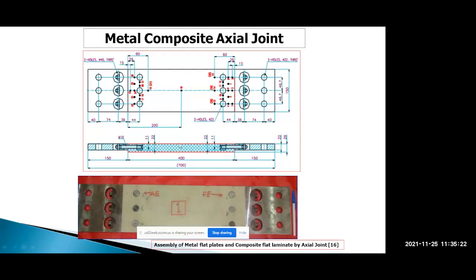Here you can see a composite plate joined with two metallic plates on either side with axial joints. A long hole is made on the face of the composite plate and on the side face of the metallic plate, and a long stud is put. Here the nut is tightened, here an insert is there, and the stud is matched here. That's how we get the axial joint. It looks like a very simple joint, but it is very complicated to realize, because we have to make a very deep hole in the composite laminate, again along the layers, along the thickness side. So we face a lot of delamination, drill drifting, and all those problems, and we have to make the hole in composite carefully.